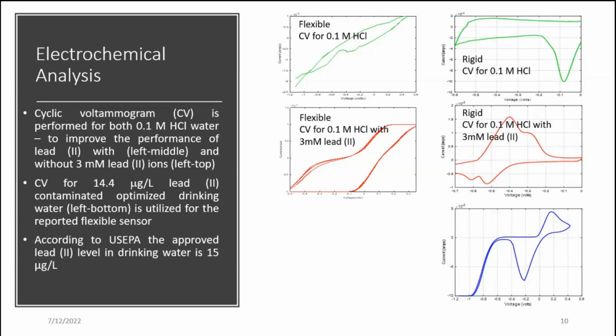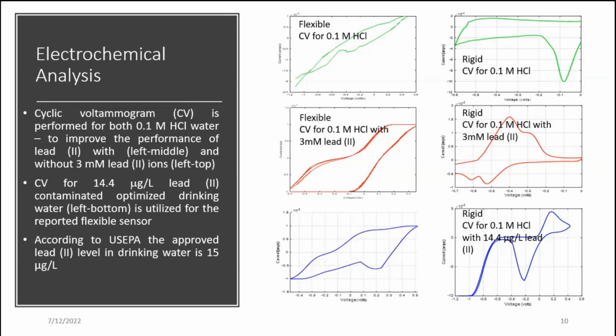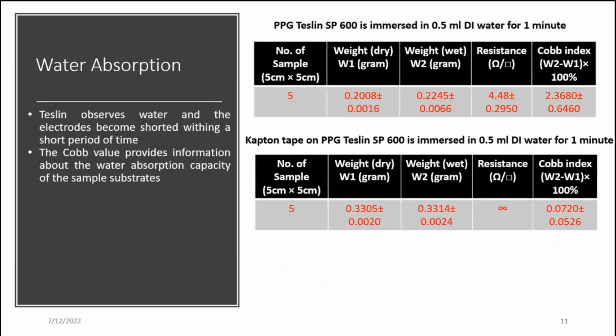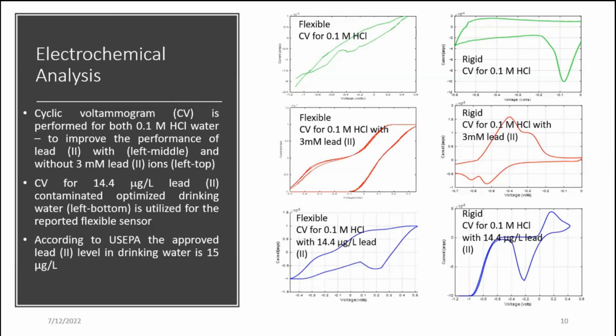So this one is the CV for 14.4 microgram per liter, where we can see a very nice deposition and a stripping peak. This was for our flexible one for 14.4 microgram per liter lead. We can see the peak is flattened, but then again, we can see at approximately 180 millivolt some peak. But we have validated our fabrication processes, right? But something probably went wrong, because we do not see as optimum a result as we were expecting for our flexible sensor. So what went wrong?